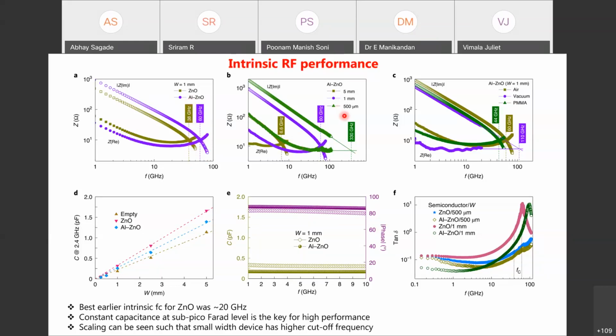So from now onwards, I will show you the data only for AZO. This is a scaling of the devices where we have shown a comparison of 5 mm, 1 mm, and 500 micrometer size devices. And as you can see, the cutoff frequency is increasing from 6.6 gigahertz to 60 gigahertz to 330 gigahertz. Okay, so this 330 gigahertz is the maximum cutoff frequency which is reported for any material other than III-V materials.